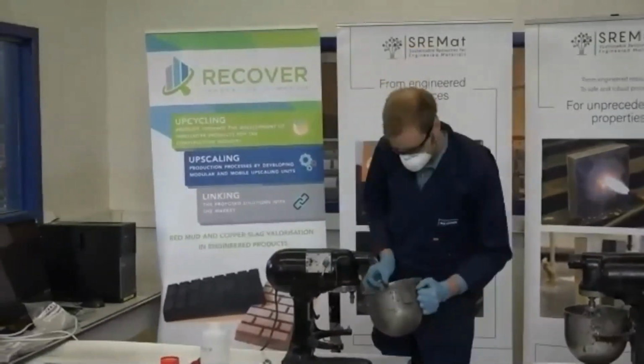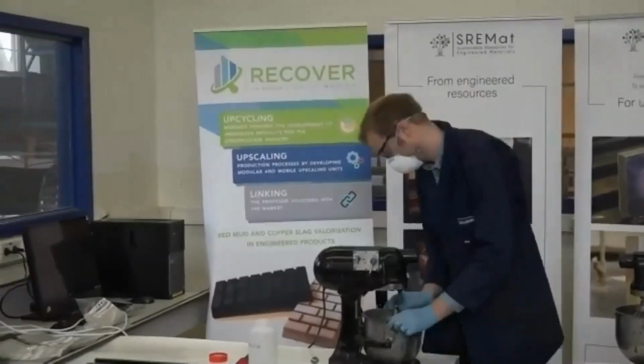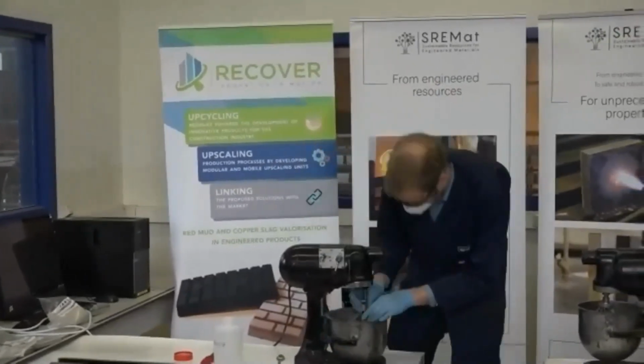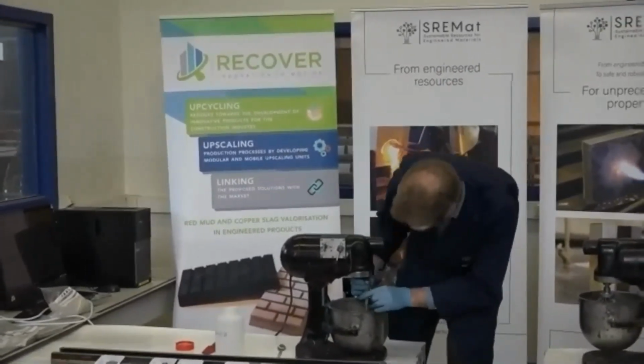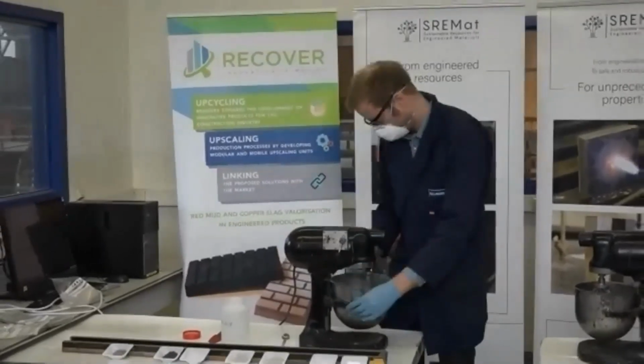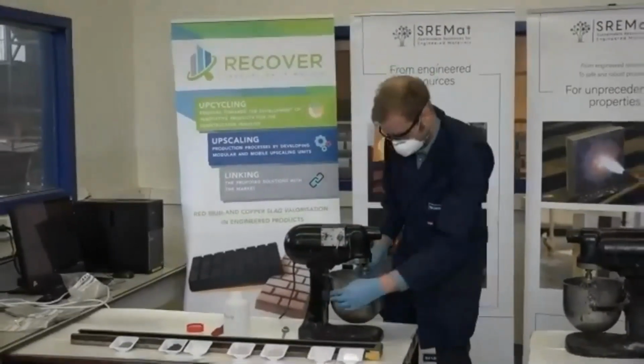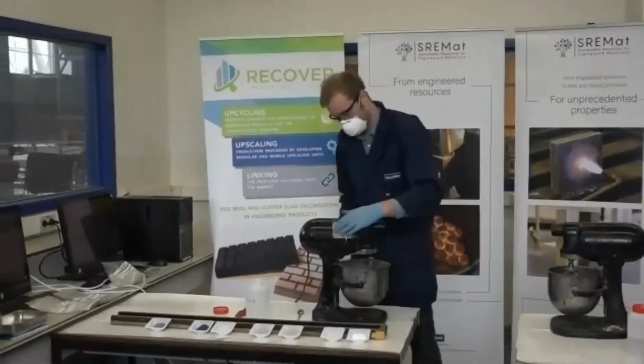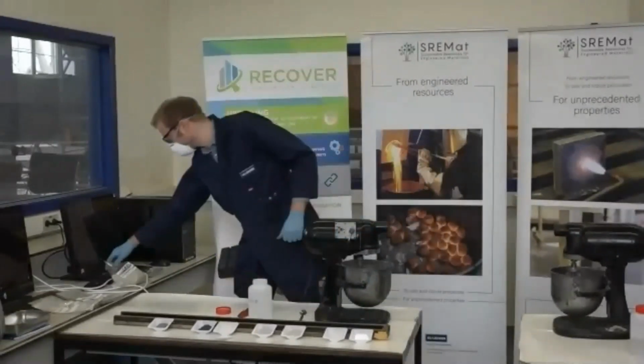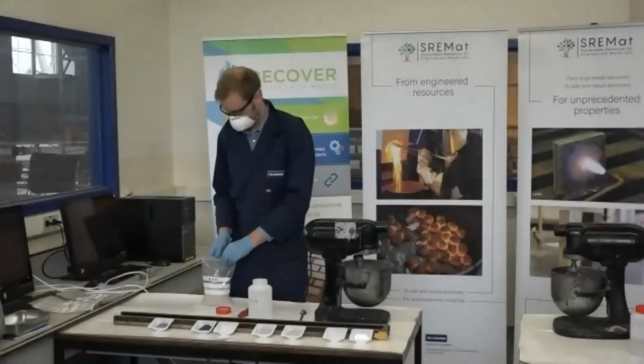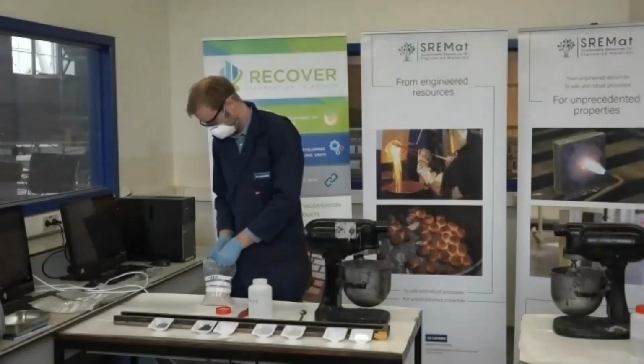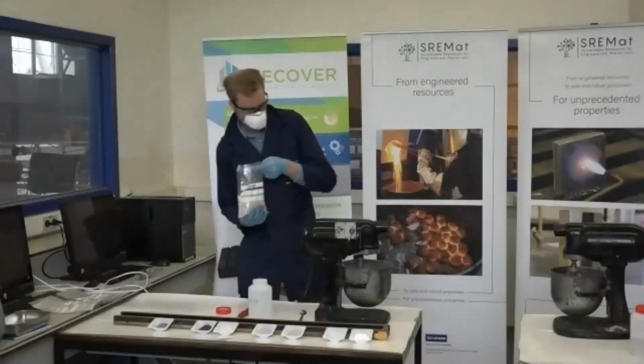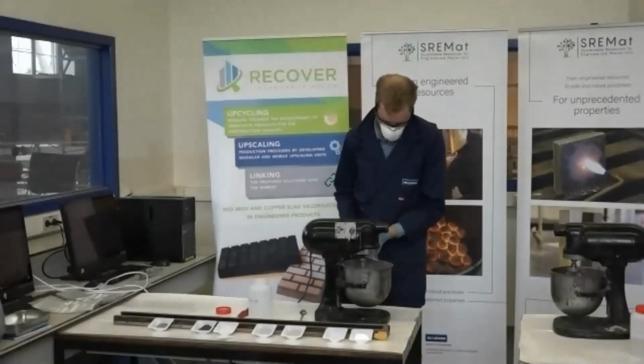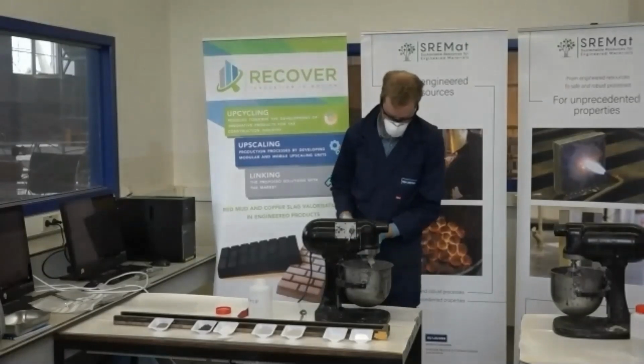We basically can, with these hybrid binders, use these additives and can limit the liquid that we added at the beginning as much as possible. And the last step, we still want to also add the aggregates. That was the sand in this case. Which is now slowly added to the binder mix.